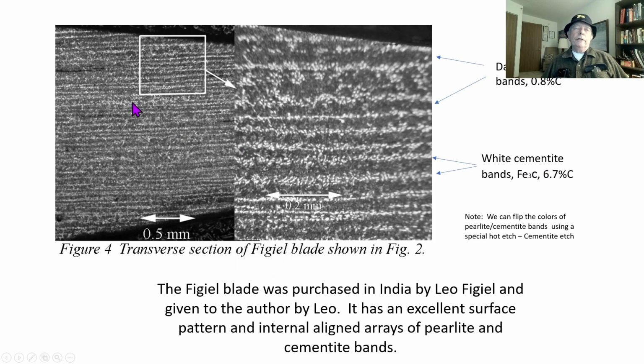Leo Figiel, in one of his travels to India, in this case it was Rajasthan, India, right in the middle of the country, acquired about an 8-inch long blade. It was highly corroded, but he thought it might be good because it had a gold inlay at one end, so he gave it to me, and we etched it. And lo and behold, it had one of the best patterns on the surface, and one of the best internal patterns of any blade we've ever looked at.